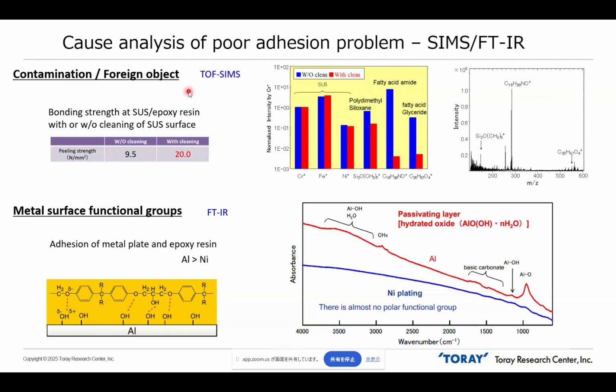It is also important to analyze poor adhesion or peeling problems. In this upper example, we would like to consider the adhesion strength between SUS and epoxy resin. Before cleaning of the SUS surface, the sample has poor adhesion; after cleaning the surface, the adhesion strength becomes much better. Then we examined the surface of SUS by using the TOF-SIMS technique. We detected these kinds of organic impurities at the surface before cleaning. These organic impurities are a very small amount, but they can be a cause of poor adhesion or peeling problems.